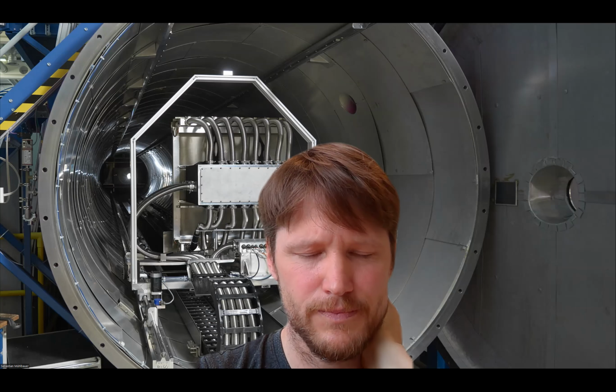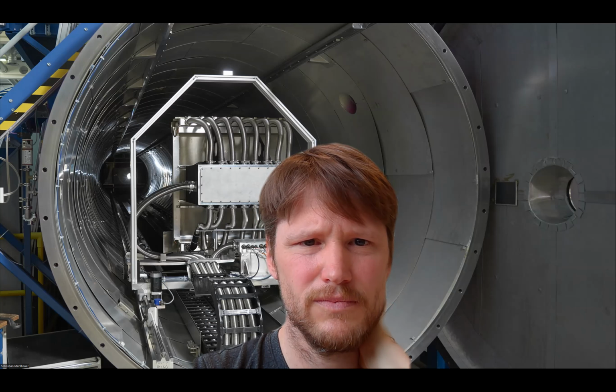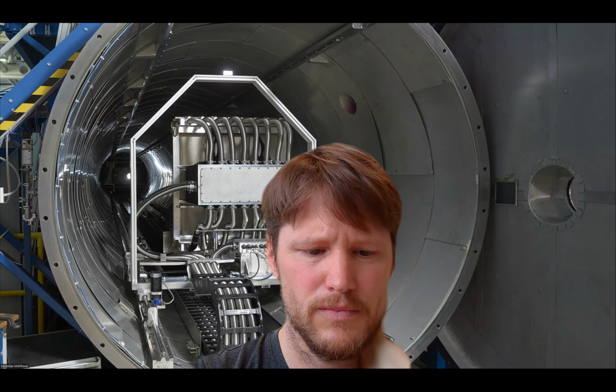Right now. So even in the monochromatic case, we have to first measure the scattering under certain conditions of temperature and field in the superconducting state. That's what we call the foreground. And also we have to measure the scattering out of the superconducting phase. And that's what we call the background. And then we will subtract the background from the foreground, and then we will end up with our signal. So in our signal, we will be observing the actual Bragg reflections coming from the vortex lattice in the superconducting phase.